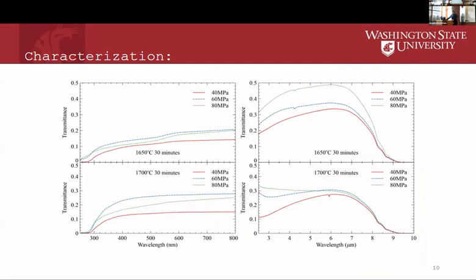Moving on, we got to the characterization of our pellets, and we looked at our optical properties in both the IR and the UV-visible region. You can see blown up pictures of these graphs here, and especially at 1650 degrees C, we got significantly higher performance in the IR region than we did in the visible region.